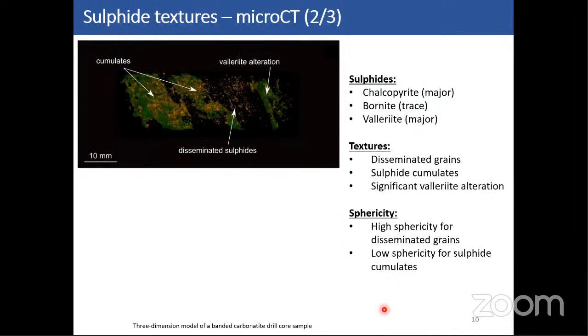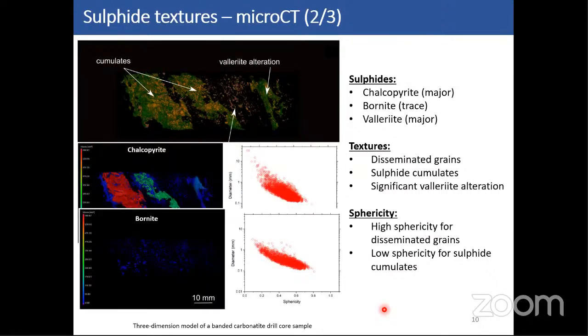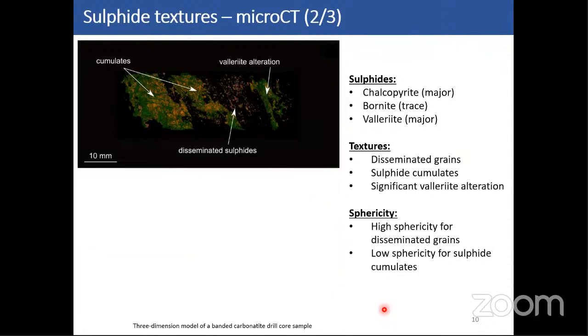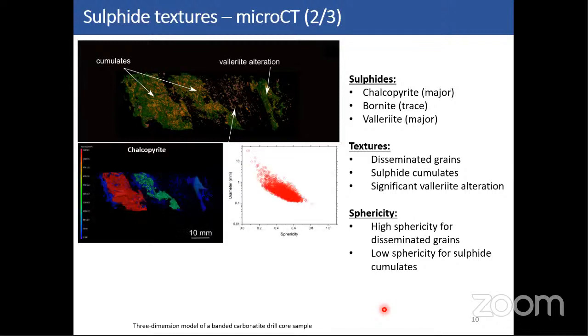With this other banded carbonatite sample, you see exactly the same feature. This domination of chalcopyrite over bornite in terms of primary sulfides, as you can see in these two heat maps. But the main difference is a concentration of valleriite here, which is very important. And something also very interesting is that valleriite is exclusively present together with primary sulfides, such as chalcopyrite and bornite. And there is no presence of valleriite veinlets as observed with the mineral liberation analysis. But otherwise, it's possible to see exactly the same texture: sulfide cumulates, disseminated grains, and the sphericity pattern is exactly the same.